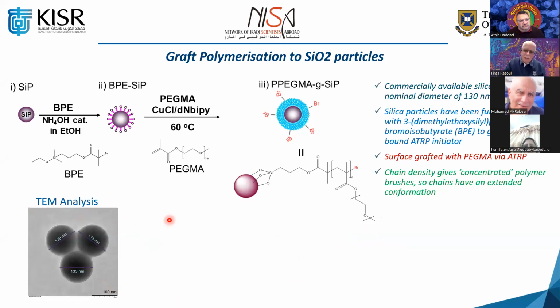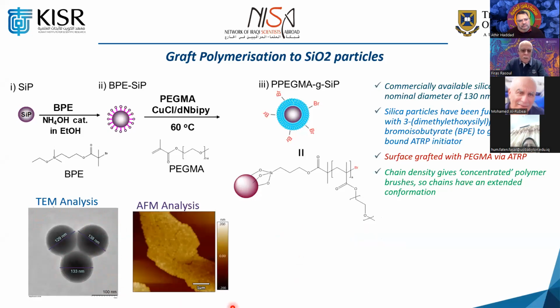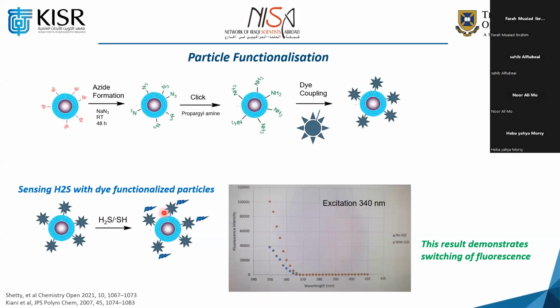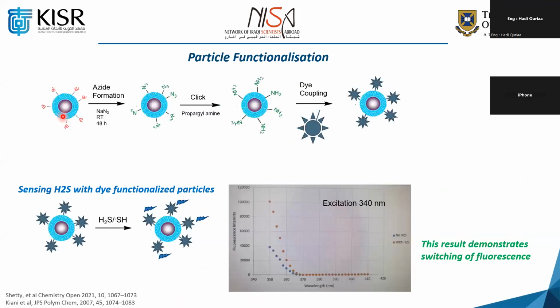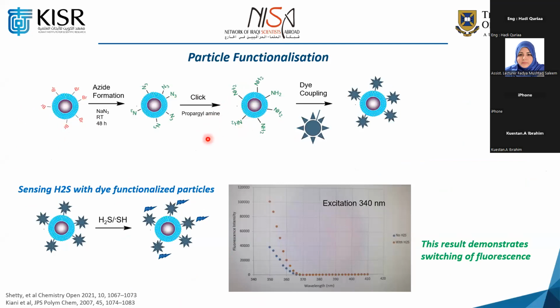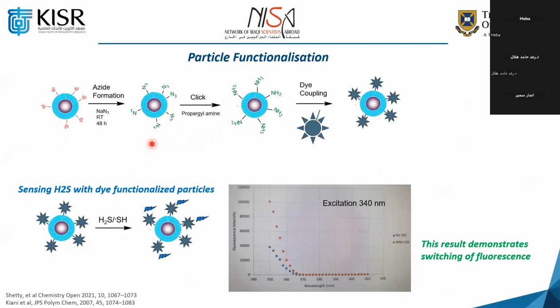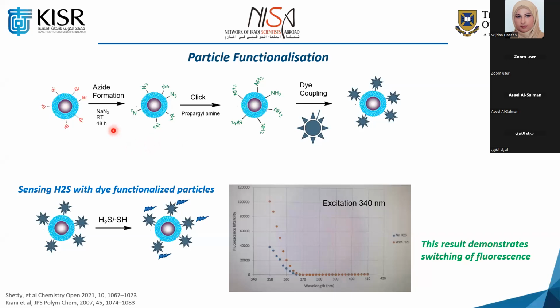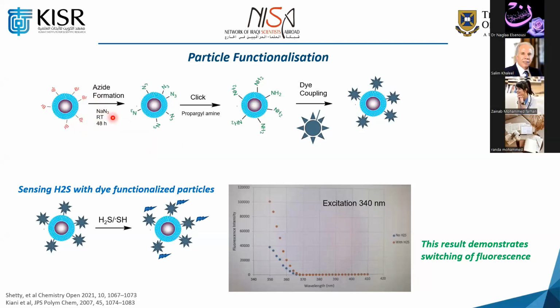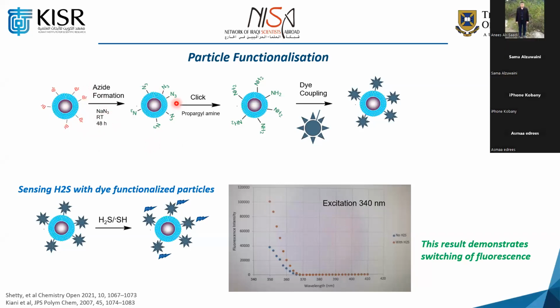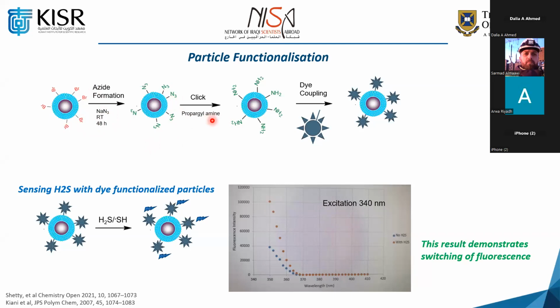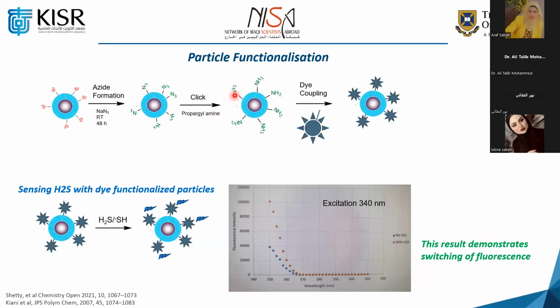Of course, we did some characterization, transmission electron microscopy. You see the size and the size distribution of these nanoparticles we made. We also did AFM analysis. After we did that, we went on to do functionalization, putting the dye, the pigment which we synthesized earlier, into it, using this bromo compound. Using similar chemistry, convert the bromo to azide, the azide with propargyl amine, we convert it to an amine group by click chemistry. Then we couple the dye, same chemistry as the previous one.